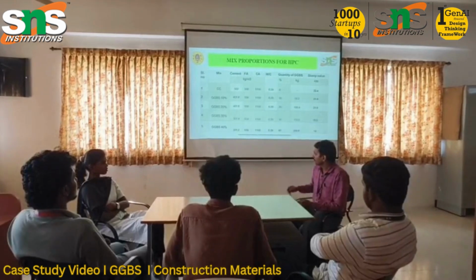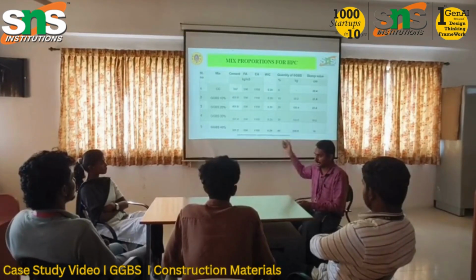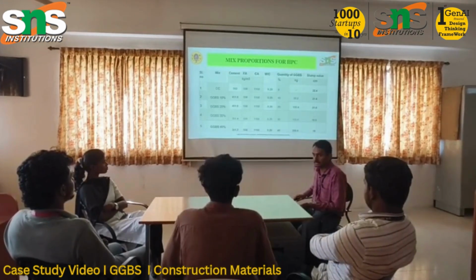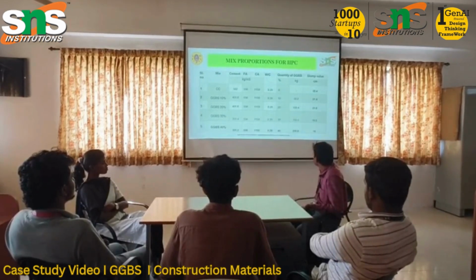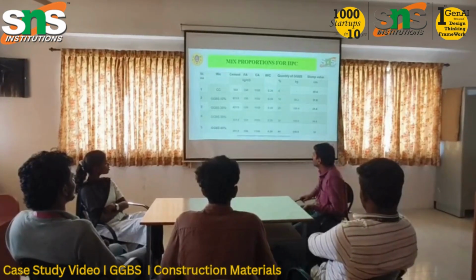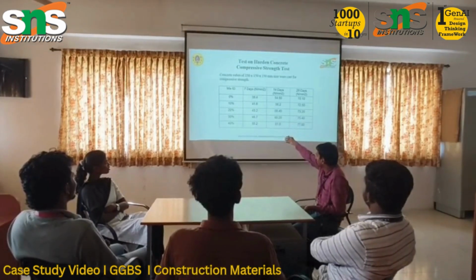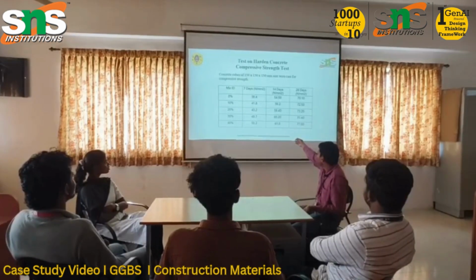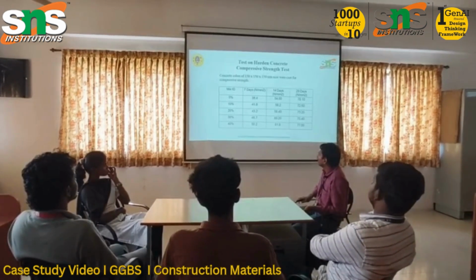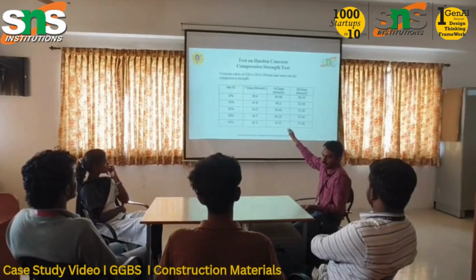What we have observed during the test is, if you use 40% replacement of GGBS, you will get high strength as well as an optimized slump value, and also highly durable concrete. The slump value is 18. The compressive strength obtained is 50.2 at 7 days, 61.8 at 14 days, and at 28 days a maximum peak value of 77 Newton per mm square on using 40% GGBS replacement of cement.